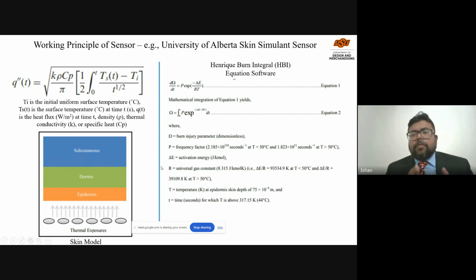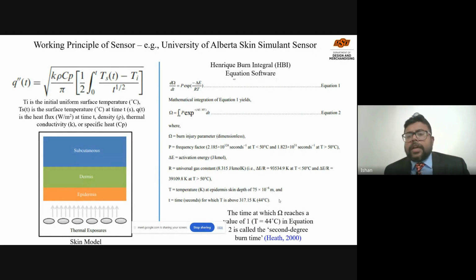So if you ever do this test, most of the time you have the sensor. From the sensor, you get the heat flux. Then your sensor has to be coupled with the software. That software can measure the second degree burn time, that I told you in the beginning. It measures the burn injury parameters for the clothing. So the time at which this omega value reaches 1, that is T equal to 44 degrees centigrade in equation 2, is called the second degree burn time.